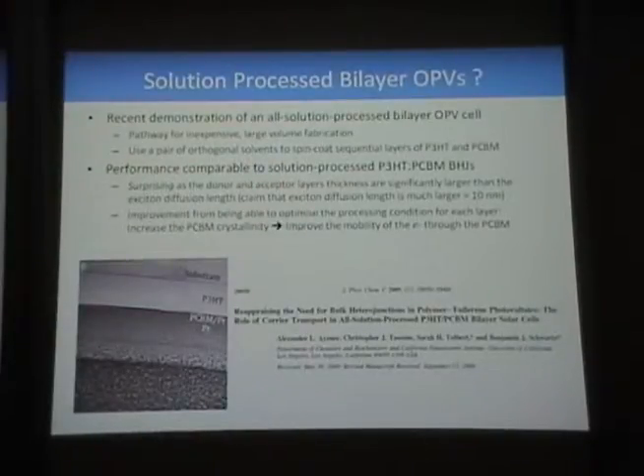Now recently, the group from UCLA demonstrated an all-solution processed bilayer OPV cell. If it's true, this is quite exciting because this provides a pathway for inexpensive, large volume fabrication. The key technique here is to use a pair of orthogonal solvents, in this case dichlorobenzene and dichloromethane, to spin coat sequential layers of P3HT and PCBM.